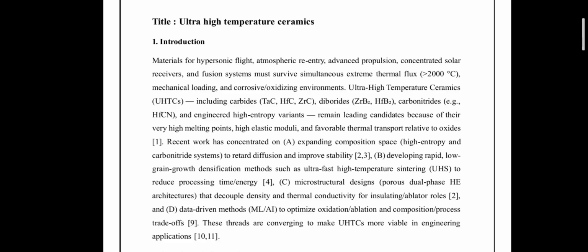Current research is therefore focused on four main directions. First is the composition expansion, especially high entropy and carbonitride systems, to slow down diffusion, suppress phase instability, and improve the thermal and chemical properties. Second is advanced densification routes, such as ultra fast high temperature sintering, which dramatically reduce the processing time and grain growth, while cutting energy consumption.